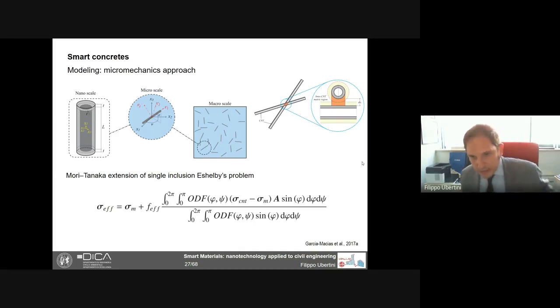But what's very important is that when we do this averaging, we have to consider the orientation of the nanotubes. So we do a sort of volume average of the properties of the nanotubes, considering their orientation distribution function, that is this ODF. Well, if we disperse the nanotubes randomly, this ODF is just 1 in all directions because we have the same probability of having the nanotubes oriented in any direction. But then if the material is strained because it's under compression, for instance, then of course nanotubes tend to align in certain directions with respect to others. So the orientation distribution function will change.